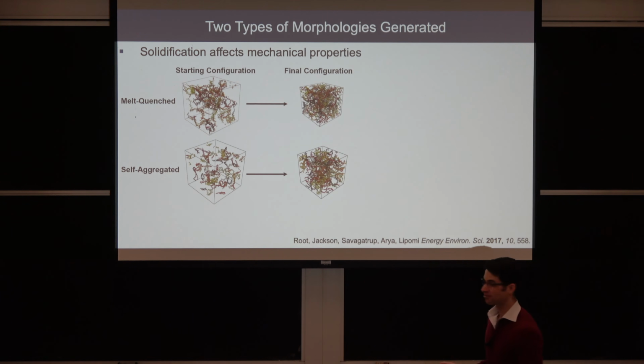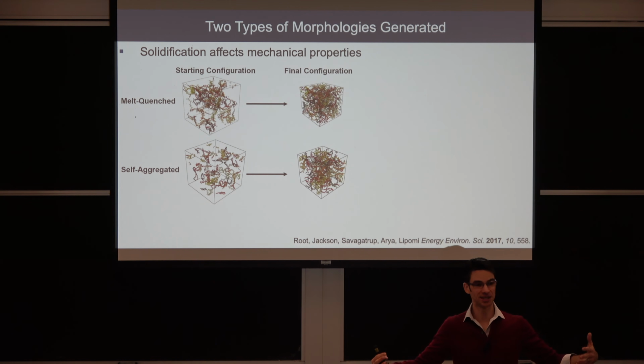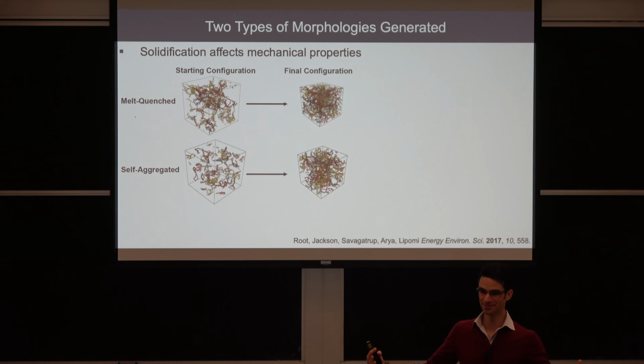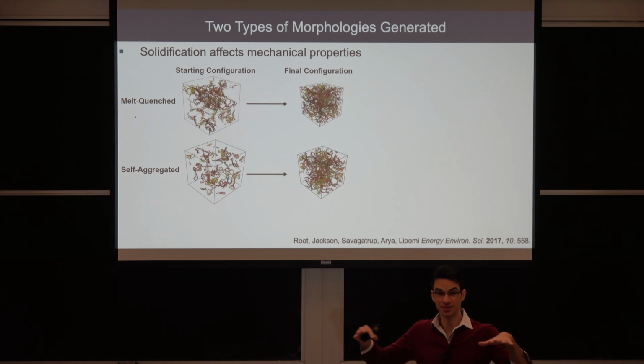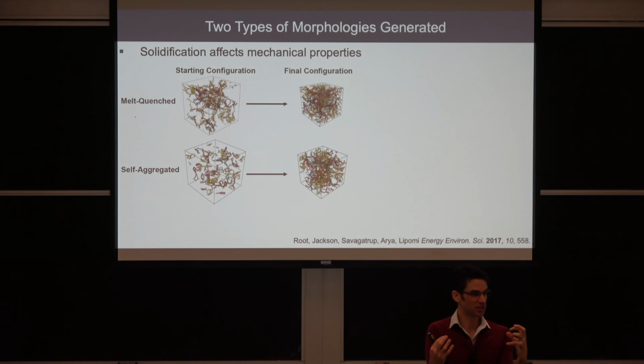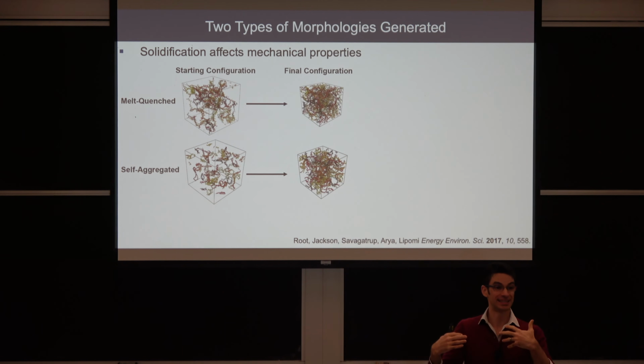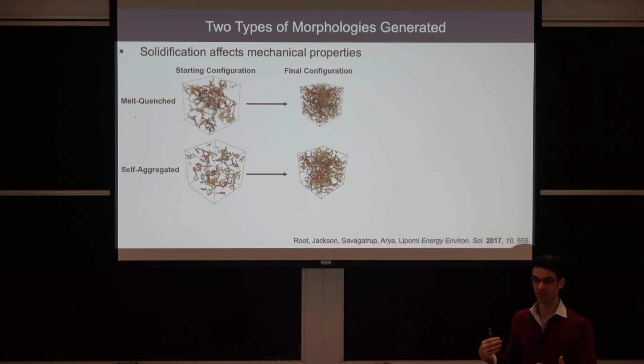You can imagine a self-aggregated morphology, which instead of melting it, you dissolve it. And not only do you dissolve it, but you dissolve it in a bad solvent, where the polymer molecules shrivel up on themselves because they don't want to interact with the solvent. Then when you evaporate the solvent and you solidify the film, the polymer molecules are already balled up. They're already kind of aggregated. They form this low density film that's predicted, at least by these simulations, to have a low density of entanglements.